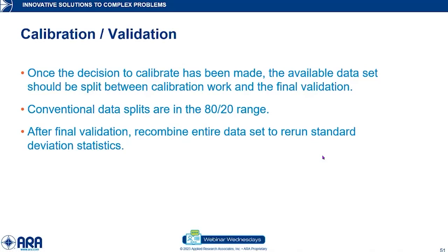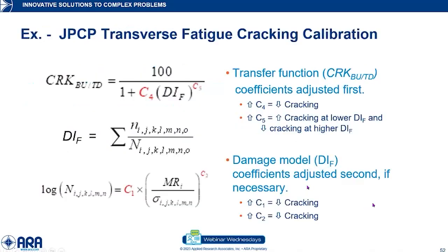In other words, 80% for calibration, 20% for validation. So when we validate, after we validate the calibration, in other words, we're using this independent data set, and it checks out. It's matching what's being predicted with the new local calibration factors. So then we recombine the entire data set and then we rerun it in order to get the standard deviation. Standard deviation is important because that impacts the reliability level in the pavement design program. So the lower the standard deviation, that means that basically you can avoid over-designing pavements.